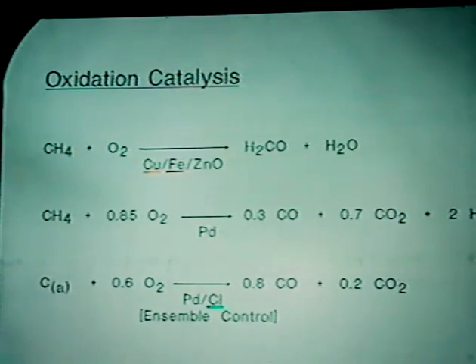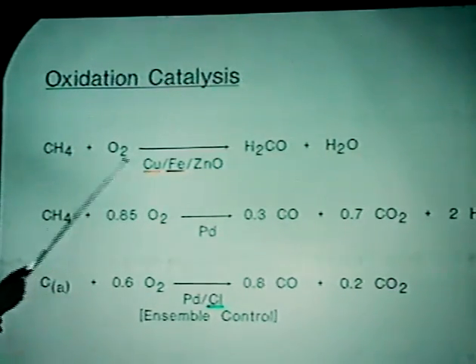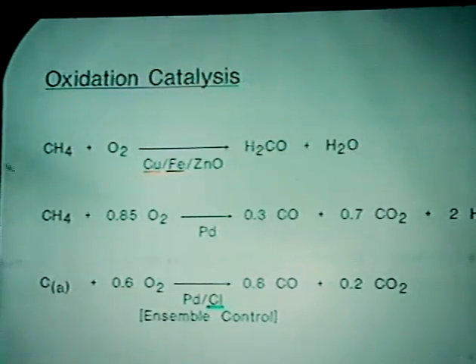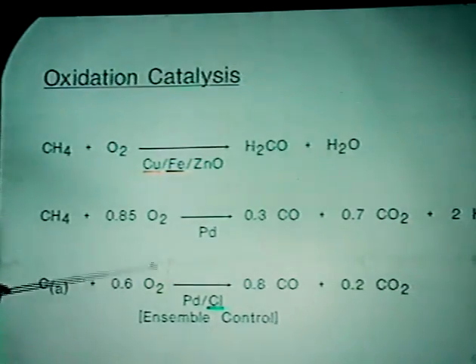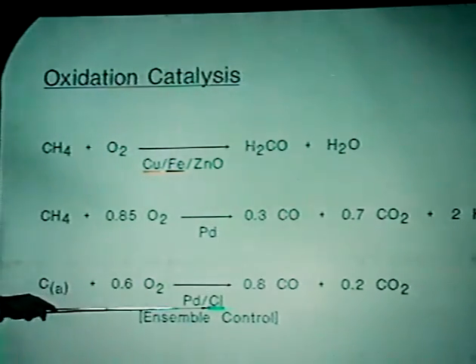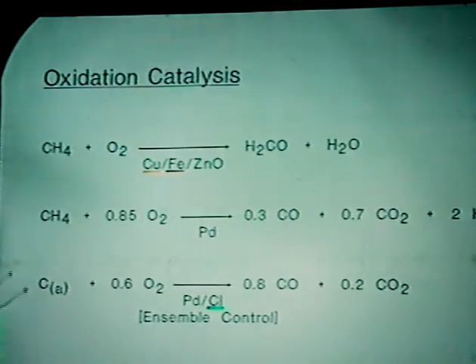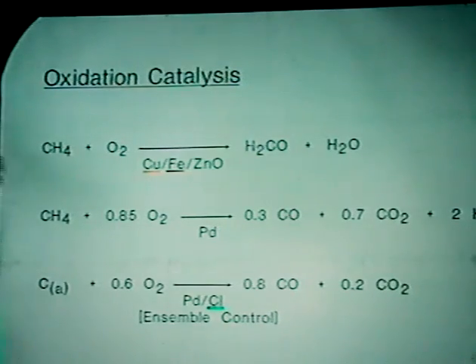So what principles did we use here in the oxidation to formaldehyde? We made these Coulombic pairs, and basically it's chemical control by two redox systems and Lewis acid at the same time of the chemical reaction. In here, the control was also chemical, but then it became geometric when we added chlorine and confined the ensemble so that we got more CO and less CO2. So this is the oxidation catalysis. I claim I have used principles.